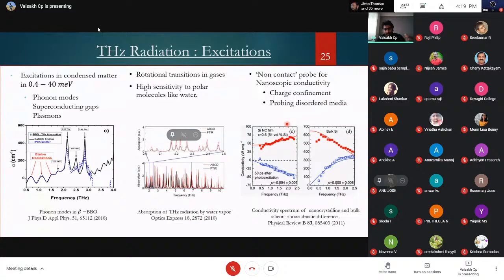Just as an example, I've shown here the terahertz spectrum from a big bulk crystal and one from a silicon nanocrystal. They are different because the conductivity dynamics is different in these two systems. By looking at the terahertz spectrum, one can arrive at relevant conclusions from this.